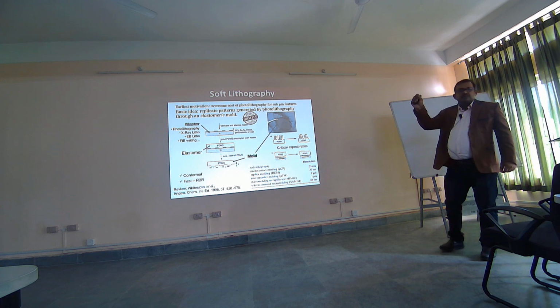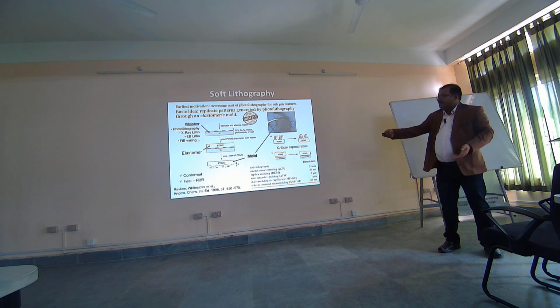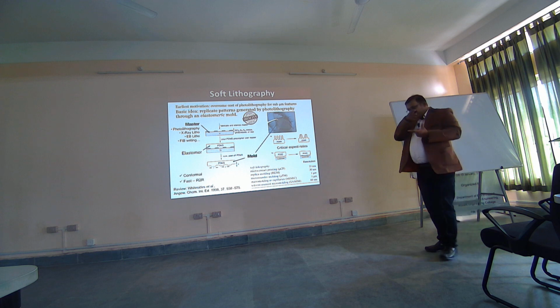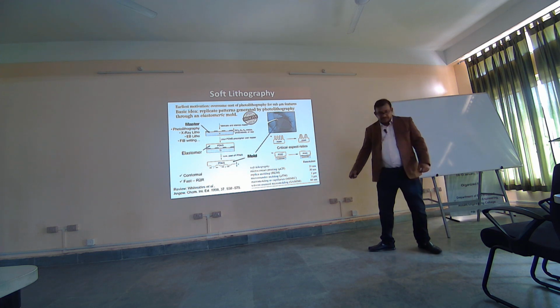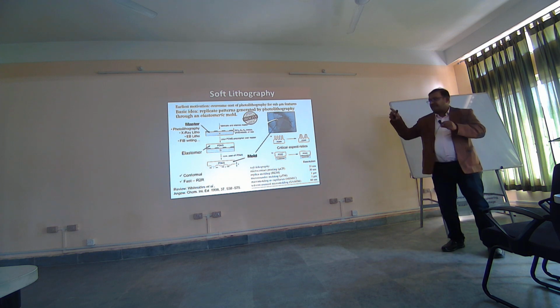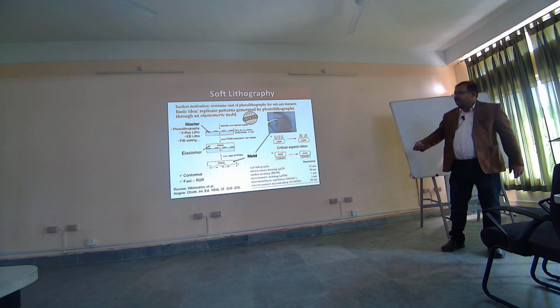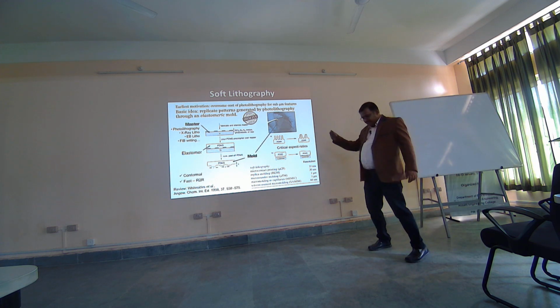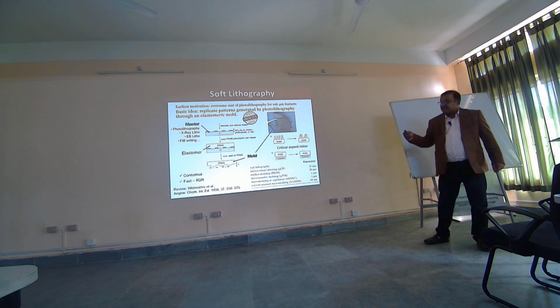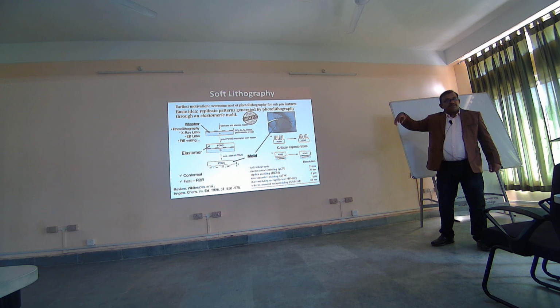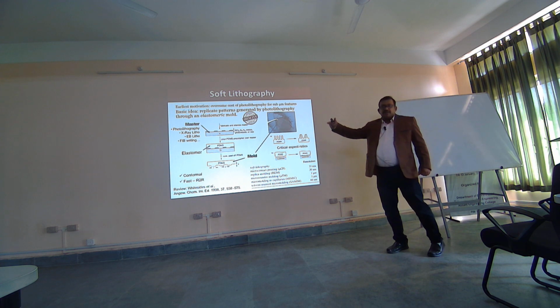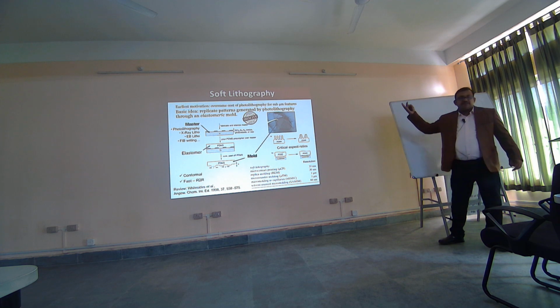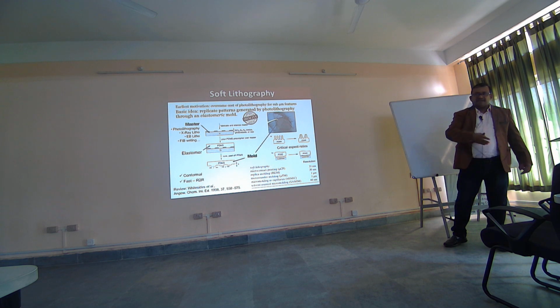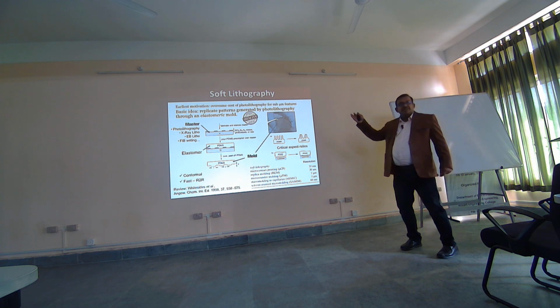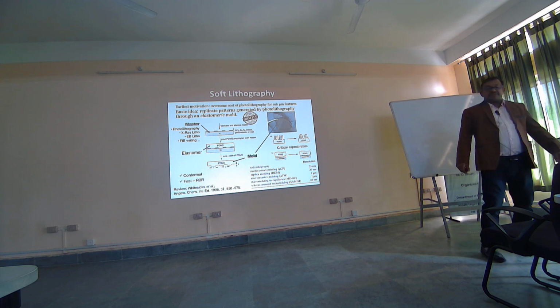Okay, so the reason is because this patterning, we will use mask, right? And the mask and the patterning, if we want to develop some pattern on the substrate, the process by which this happens is basically, I will illuminate it by a certain beam of light, especially when it is photolithography. So in that case, the pattern that I am able to successfully transfer will be limited by the diffraction limit, okay, and which will be limited by the wavelength of the light used. So the entire aspect is that you simultaneously go on reducing the wavelength of light, and that has happened in the past, and that is how miniaturization trend has continued for close to 5 to 6 decades now.